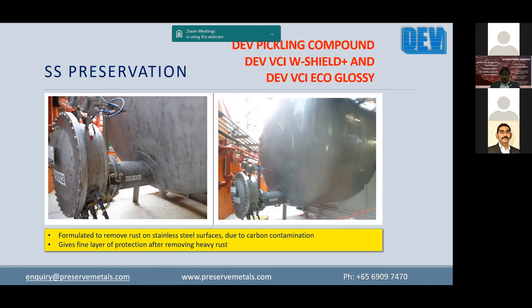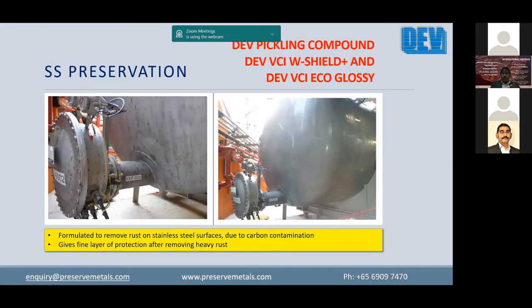To prevent that, we have a set of solutions, called the DEV pickling compound, which removes the contamination, only the iron oxide, without damaging the chromium oxide layer. After that, the surface is neutralized with the DEV VCI W-Shield+. And finally, we use the DEV VCI Eco Glossy, a water based paint coating, which ensures that even if any residual contamination remains in the stainless steel, invisible to the eyes, we are still able to protect against it popping up, and the stainless steel metal surface continues to remain in the same form.